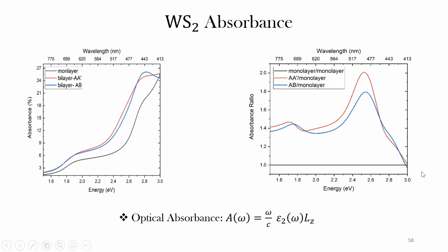And so far, no study has been done for tri-layer cases, so we have calculated also for tri-layer cases. This shows that if we have TMDCs and we go to bilayers, there is going to be some increase in this region from 2.4 to 2.6. And there is going to be an absorption peak around 1.8 in bilayers. Next.